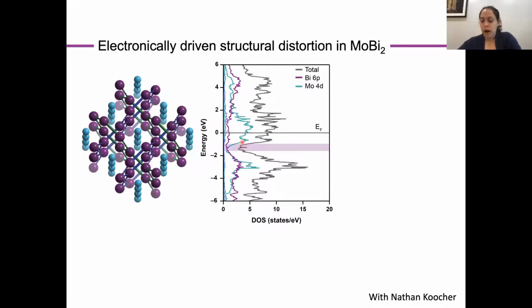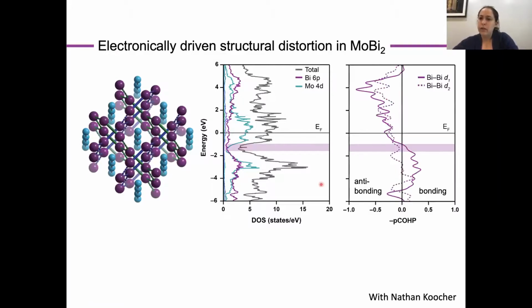I think more evidence for that is gained when we look at the crystal orbital Hamilton population, in which we assign bonding and antibonding character to these states and then localize it towards relevant interactions. And so if we just focus on the D1 interaction between bismuth and bismuth, we can see that indeed the pseudogap roughly corresponds to a transition point from occupying bonding states to antibonding states. And there's a couple of important implications for this, which we can test to see how well they hold.